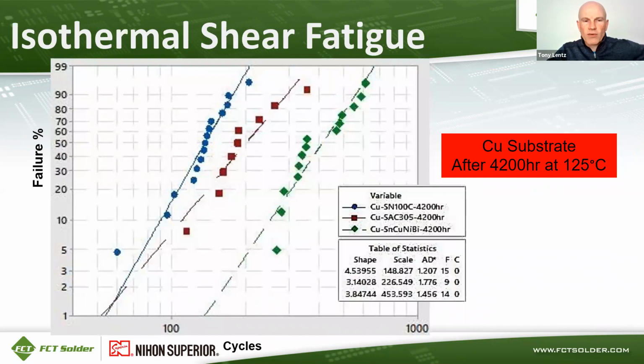And here's another data chart showing after aging of 4200 hours at 125 C. Once again, these curves have moved around, and SN100C and Sac-305 are starting to intersect in terms of their characteristic life, or the number of cycles that they lasted. Whereas the tin, copper, nickel, bismuth has the longest life, or lasted for the highest number of cycles.